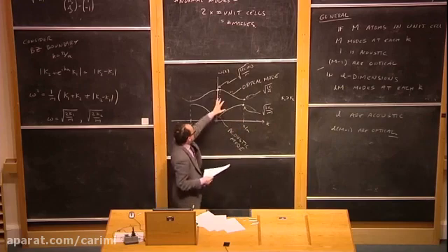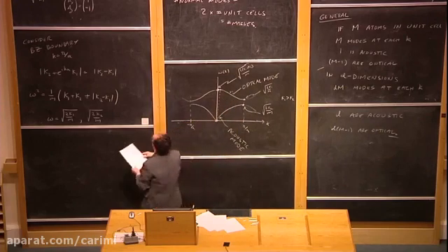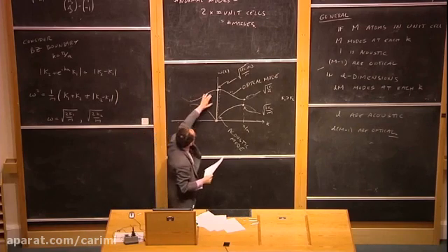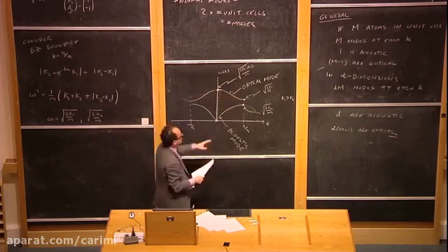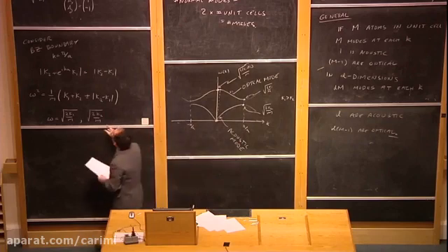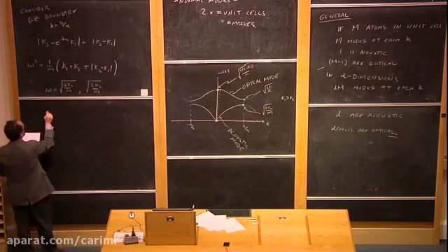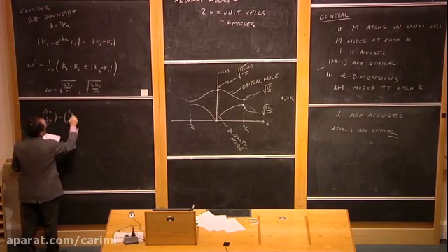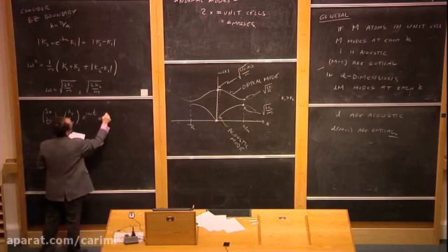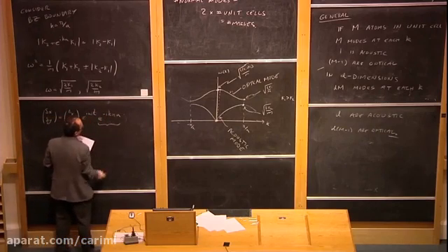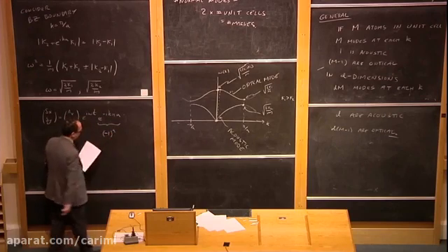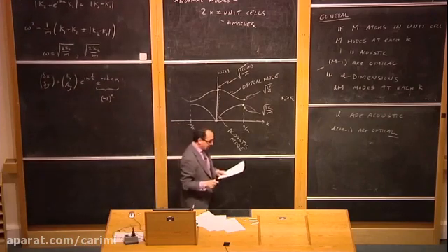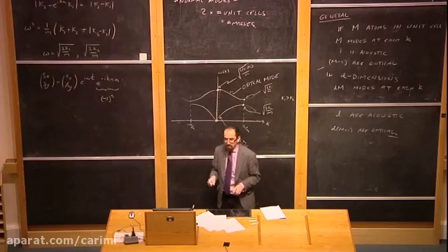Otherwise, it would be the other way around. The higher energy one is always on top. And these modes actually never cross each other. You can convince yourself by looking at the form of the frequency. These two modes can never actually cross. So what's going on at this Brillouin zone boundary? At the Brillouin zone boundary, the waveform delta x, delta y equals ax, ay e to the i omega t e to the minus i k n a. This e to the minus i k n a becomes minus 1 to the n. And that tells us that alternate unit cells are moving out of phase with each other. They're moving in the opposite direction as each other.